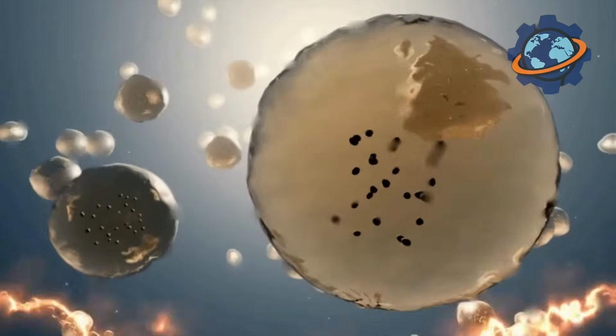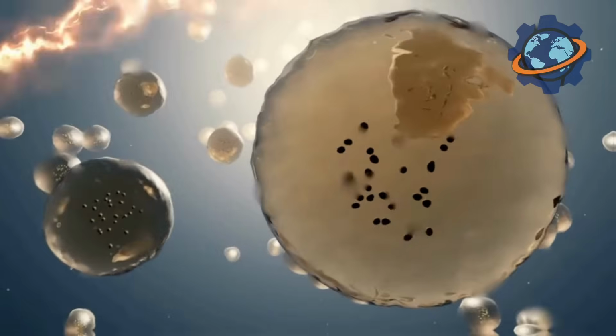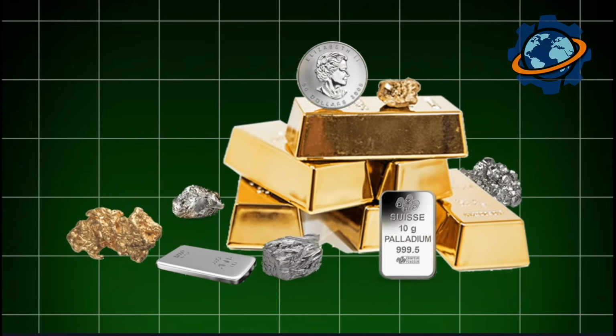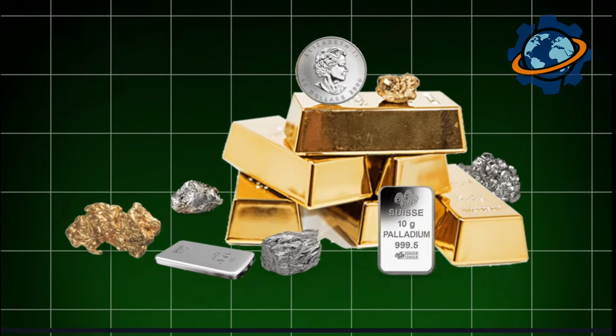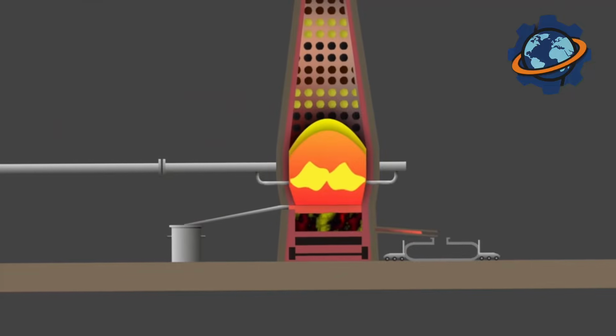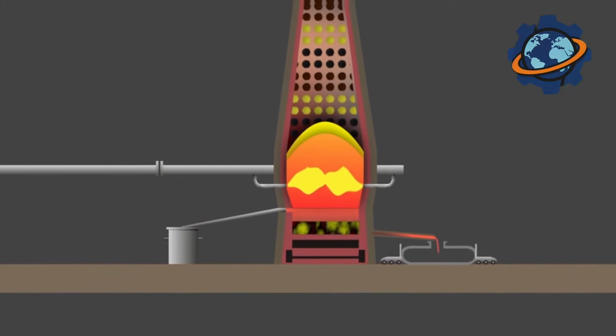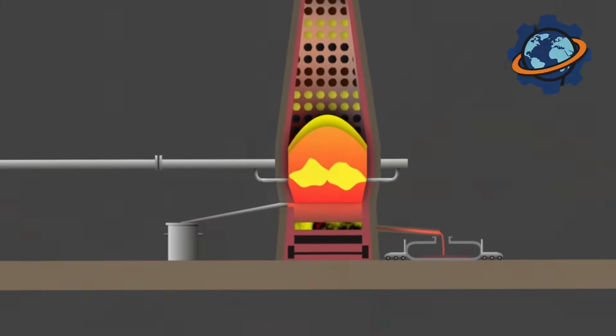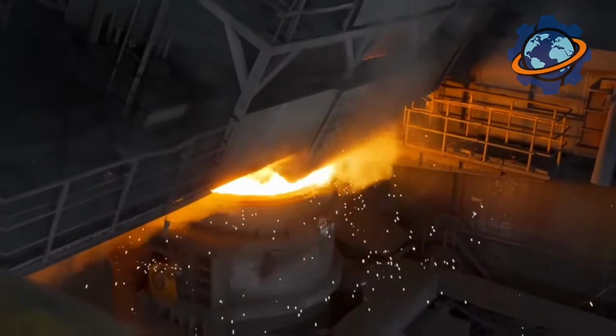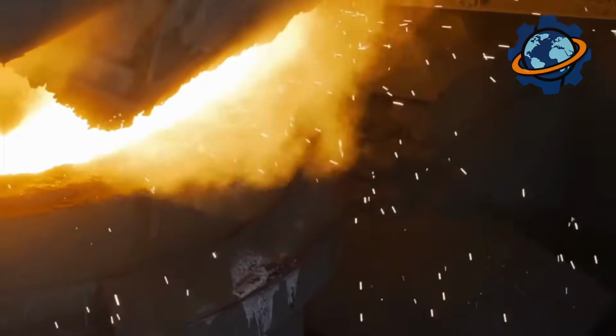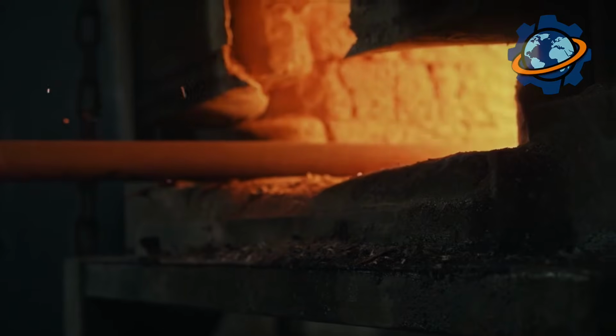Impurities like cobalt, copper, iron stay behind, falling as sludge to cell bottoms. This sludge, later processed separately, contains precious metals including platinum, gold, palladium, making waste worth more than many ores. Temperature control matters critically. Too hot, dendrites form, metal crystals bridging electrodes causing shorts. Too cold, deposition slows uneconomically.